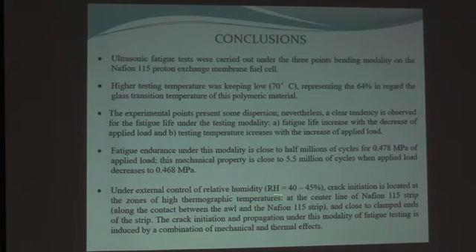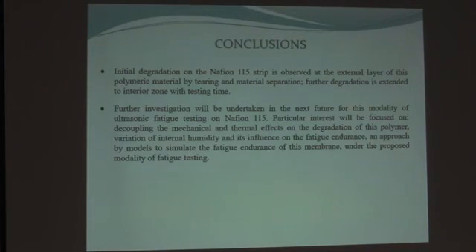Under external control of relative humidity, very important to carry out this kind of testing, 40–45%. Crack initiation is located at the zones of high temperature, thermographic temperature, at the center of the line of the Nafion 115 strip, along the contact between the horn and the Nafion strip, and close to the clamped ends of the strip. The crack initiation and propagation under this modality of fatigue testing is induced by a combination of mechanical and thermal effects.